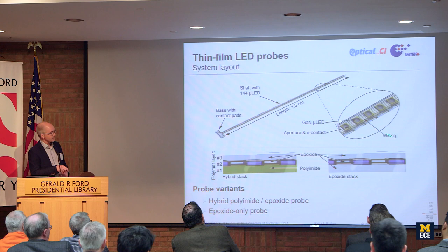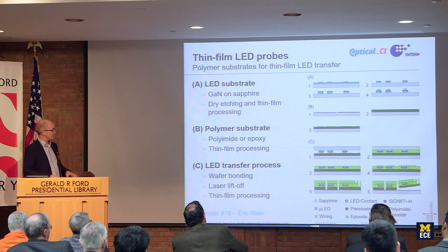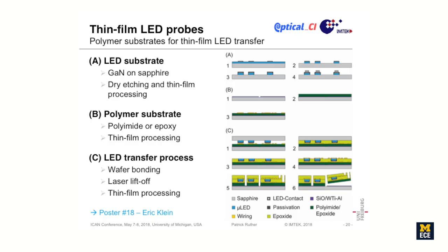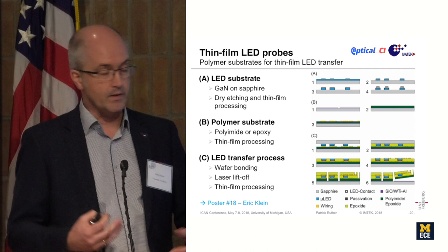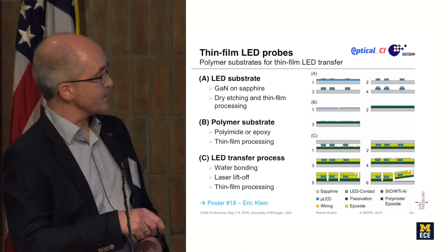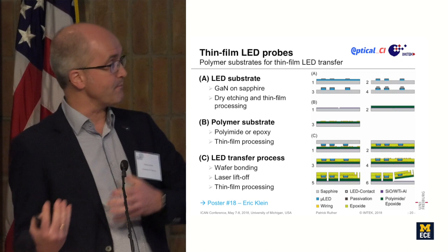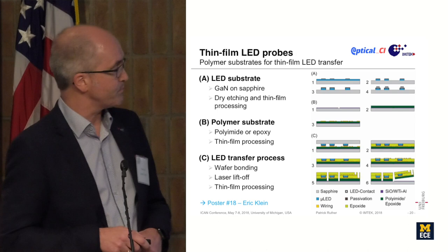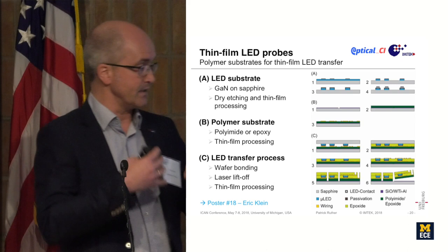Now the fabrication process is sketched here, and Eric, poster 18, can explain all the details on the fabrication process itself, but what he has to do is first pattern the LED substrate, which means gallium nitride on a sapphire wafer, applying all the metal lines and the bond metallization, in our case it's indium. Then we have the polymer substrate, which means in our case patterning polyimide or epoxy and depositing metallization, and last but not least, the laser transfer process where we bond the LEDs, so the LED wafer, onto our polymer substrate as shown here.